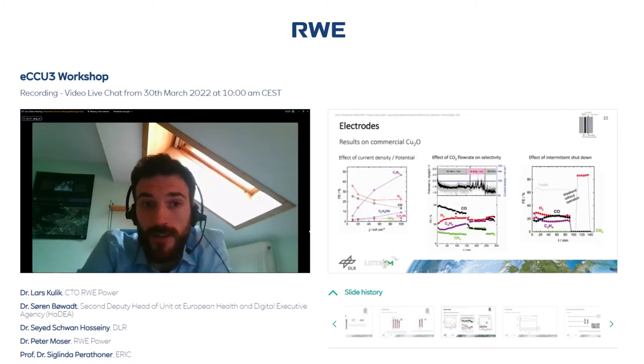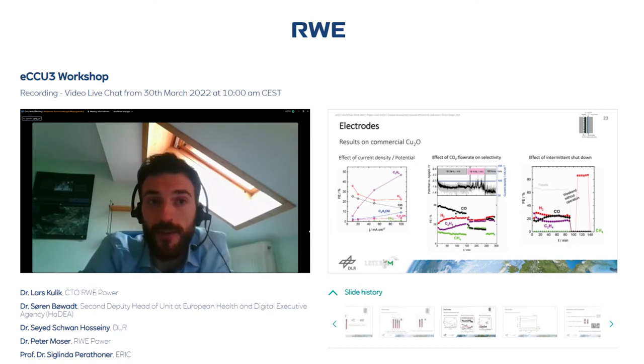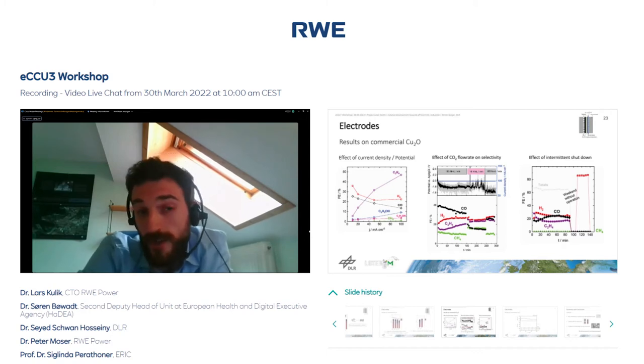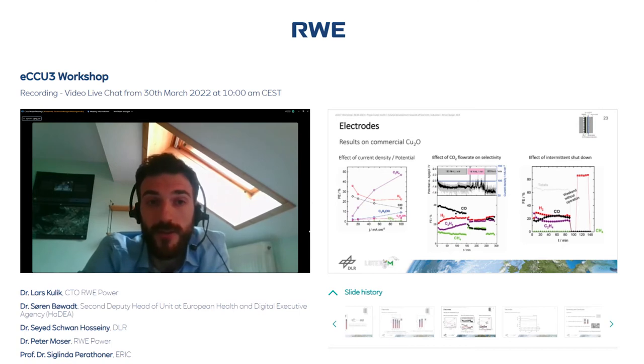And on slide 23, there are three more interesting findings, just in a kind of summary. On the left side, you can see that the current density, or the potential that changes along with current density, is responsible for different product distribution. For instance, at 100 milliamp per square centimeter, we have quite high ethylene, which we don't have at lower current densities. Now, here it would be, of course, interesting to also go to higher current densities to see how the performance is here.